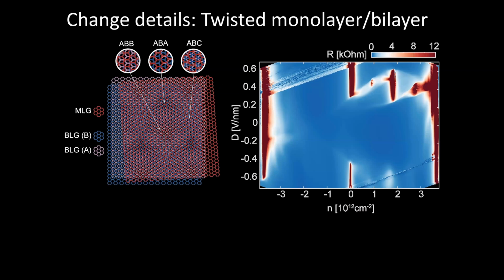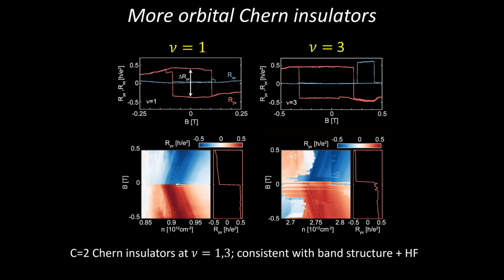Okay, so to do this, we have to move to a slightly different system. It's another moiré system: twisted graphene monolayer on bilayer. The reasons to do this were totally practical. There's nothing intrinsic. It's just much easier to reproduce the same type of physics. What you can see is that as a function of both the electric field applied across the system and the charge carrier density, you have these spikes that are happening at odd and even filling, which correspond to partial filling of these energy bands. And in particular, if you look at 1 or 3 electrons per unit cell, you see that there are indeed quantized anomalous Hall effects happening at those fillings.